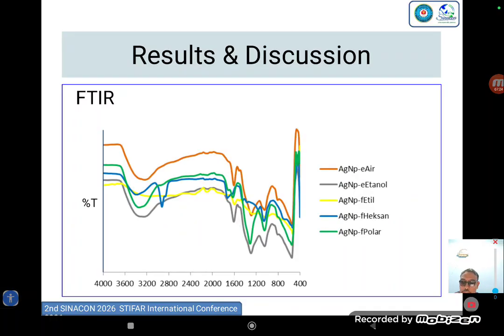To determine the presence of organic compounds acting as capping agents on the silver nanoparticles, the samples were analyzed using FTIR, as shown in the following figure. FTIR spectra demonstrate successful surface capping by distinct functional groups OH, CO, CC, which vary depending on the fraction used.